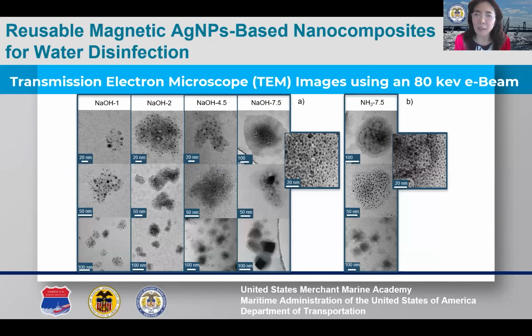TEM images of sodium hydroxide 7.5 and ammonia 7.5 revealed similar porosity and structure, regardless of the catalyst used. In both cases, uniform pores about 4 nanometers in diameter, separated by silica walls about 2 nanometers thick, were observed. The mesopore shell thickness was also found to be influenced by the amount of TEOS, increasing from approximately 10 nanometers to 80 nanometers as the TEOS amount rose from 1 to 7.5 milliliters.